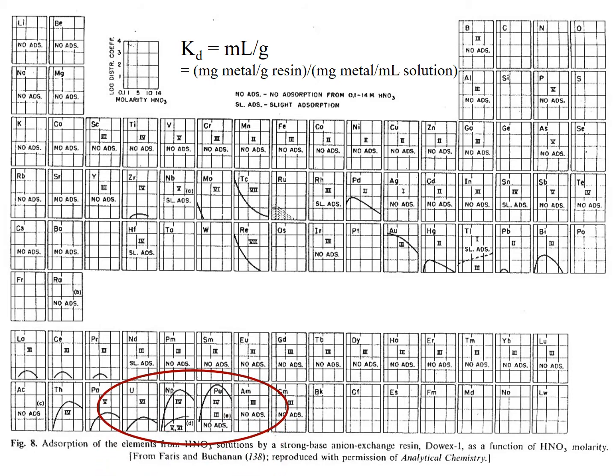For the actinides, we see sorption that peaks and decreases. Again, for plutonium, plutonium-4 has strong sorption, plutonium-3 has no sorption, neptunium-4 strong sorption, neptunium-5 and neptunium-6 limited, uranium-6 not as much as plutonium. So the tetravalents here seem to be strongly sorbed, whereas the others here are weakly sorbed.